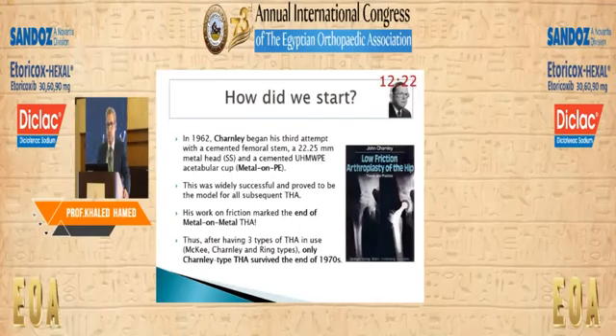So in 1962, he began his third attempt with a cemented femoral prosthesis and a small head, 22.25 millimeter, stainless steel head on ultra high molecular weight polyethylene. And this was the most successful at that time and proved to be the model for all subsequent total hip arthroplasties. His work on friction marked the end of the era of metal on metal, so that after having three types of prostheses, the McKee-Farrar, the Charnley, and Ring types, only Charnley implants survived the end of the 1970s.